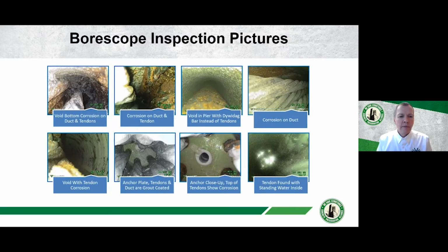And similarly, you can do this on other projects. This is a different project on a different bridge, and you can see different borescope images that were taken from different defects that were identified, holes drilled in, and then the borescope is used to determine the condition of the strands, as well as to get an idea of how big the void is. And so this gives you a way to verify in the field the non-destructive testing results that you're getting from the sonic ultrasonic techniques. And if that's something you want to do, then that's available and certainly possible.